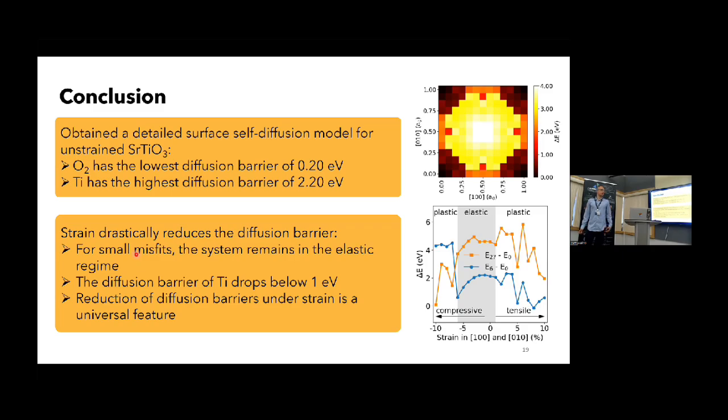No, we didn't, since we are based on the fact that we are able to produce defect-free surfaces, and so we just assume. But you have oxide formation. Now, if you do have oxide formation, you are leaving oxygen vacancies there. And in addition, they are in equilibrium with your oxygen partial pressure. So the oxygen atmosphere controls the vacancy concentration on the surface. And those are highly defective surfaces. By highly defective, I mean they can have oxide ion deficiency or different oxide ion population. Now, this will control also your cation population on the surface.